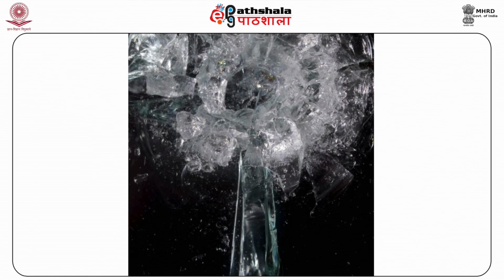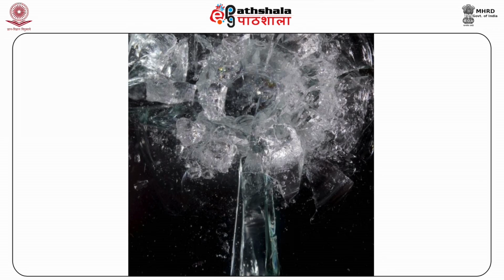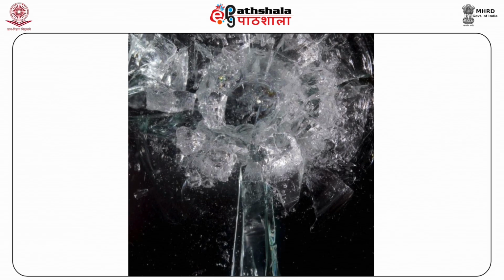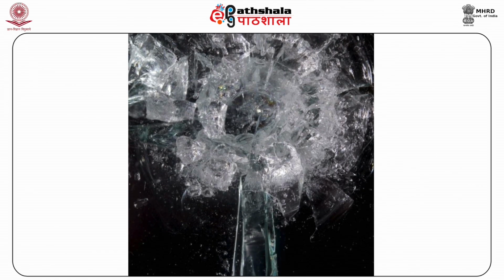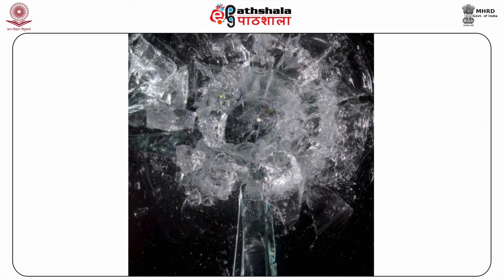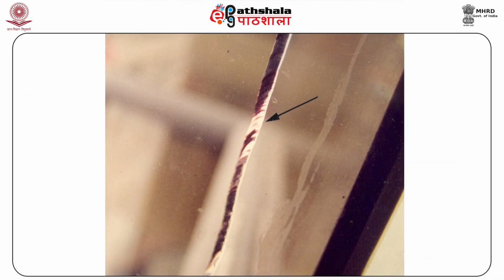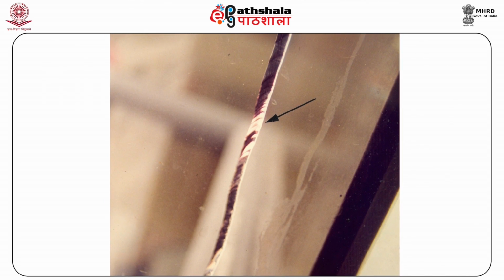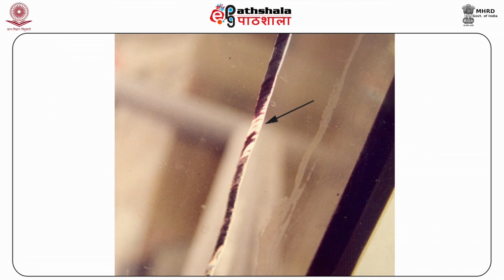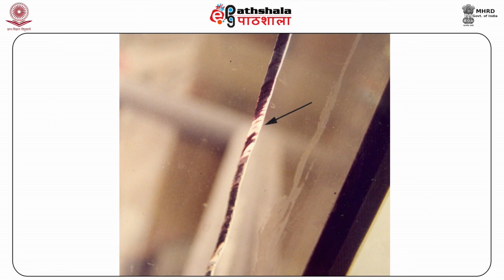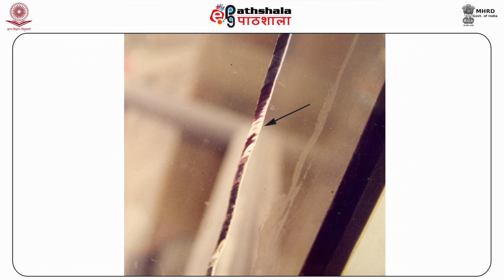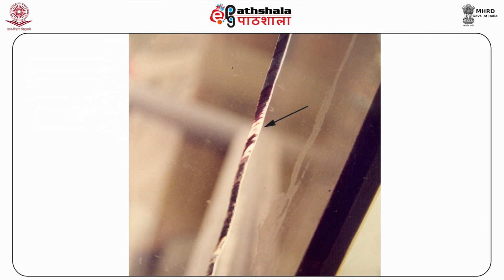The sequence of multiple impacts can be deduced when the cracks caused by a subsequent impact terminate at previously formed cracks. By observing the Wallner lines, ridges on the radial cracks, the direction of breaking force can often be determined.